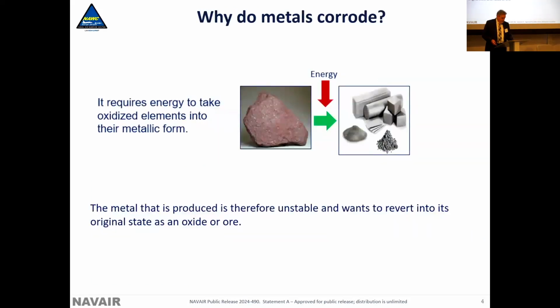Why do metals corrode? It takes energy to take oxidized elements into their metallic form. So the metal that is produced is in an unstable state and it wants to return to its oxide, which is a metal ore. So the first step in preventing corrosion is to put a coating on. Like for low alloy steels, you put zinc nickel, followed by a passivation, followed by a paint. For aluminum, you would use a passivation or chemical conversion coating, followed by a paint also.